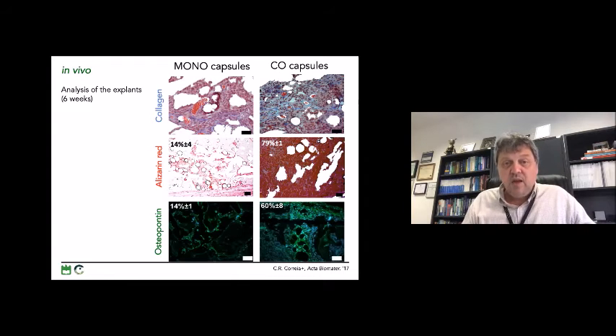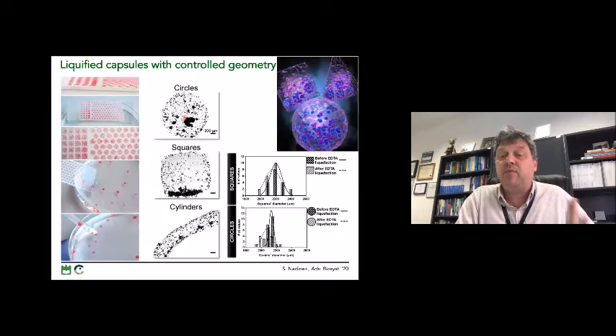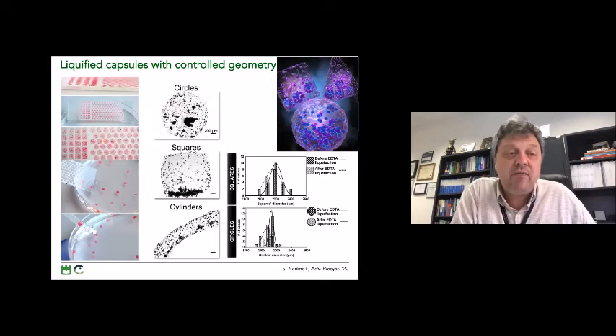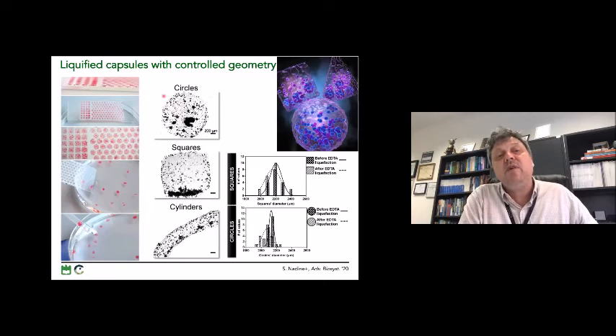So in the last 5 years in Aveiro, we were able to progress on this type of technology. We include different types of cells, including endothelial cells outside the capsules or macrophages. We tested culturing in dynamic conditions using bioreactors. So I could stay a lot more time to discuss all of this work, but due to the time restrictions, I'm just highlighting the possibility of having non-spherical capsules using patterned superhydrophobic slides with very defined geometry. So in this case, the microgels of alginate are not spheres, but they have very, very well-defined geometry. So even after the layer-by-layer coating and liquefaction, we could see that the geometries could be kept. And so we think that using this kind of elements as building blocks, we could assemble larger structures, such as in the Tetris or Lego game.